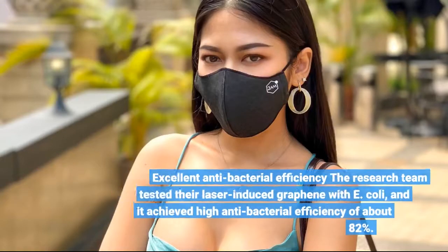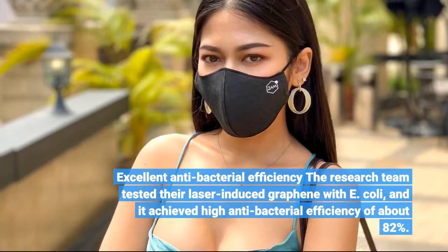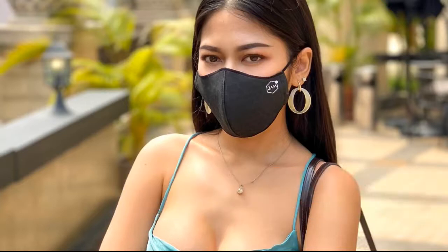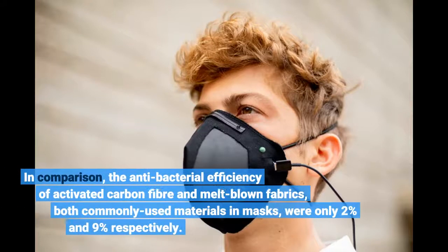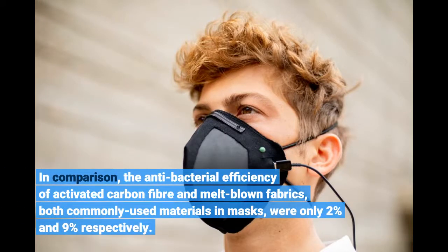Excellent antibacterial efficiency. The research team tested their laser-induced graphene with E. coli, and it achieved high antibacterial efficiency of about 82%. In comparison, the antibacterial efficiency of activated carbon fiber and melt-blown fabrics, both commonly used materials in masks, were only 2% and 9% respectively.